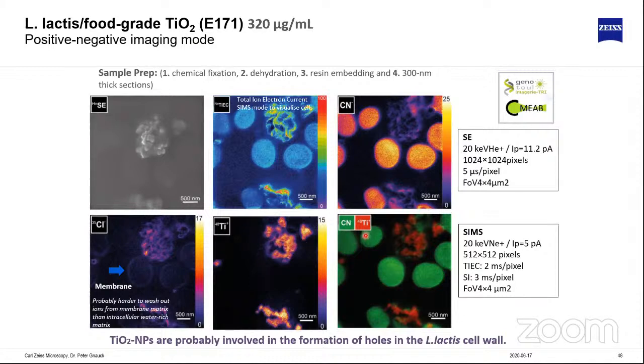And if we put the information together, then we find that cells that have not eaten up any titanium oxide, they're still okay. Cells which have eaten the titanium oxide, they're all exploded. So that's probably a hint that titanium oxide in food is probably not the very best solution. But what I wanted to show here is that we really can analyze nanoparticles also in biological samples.